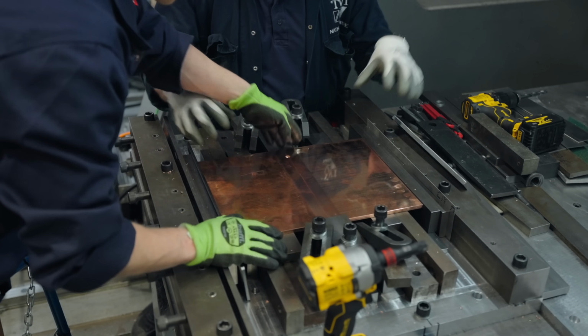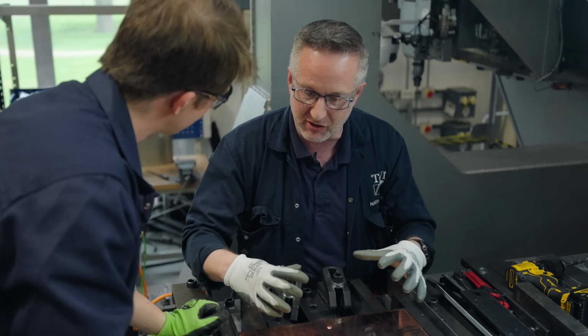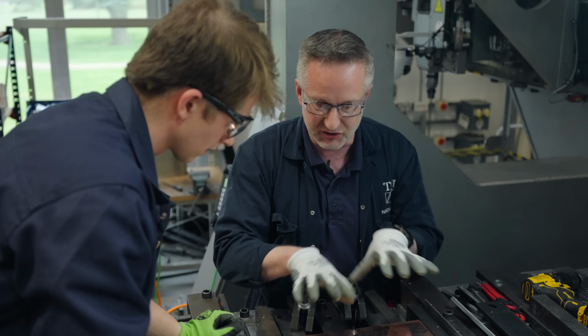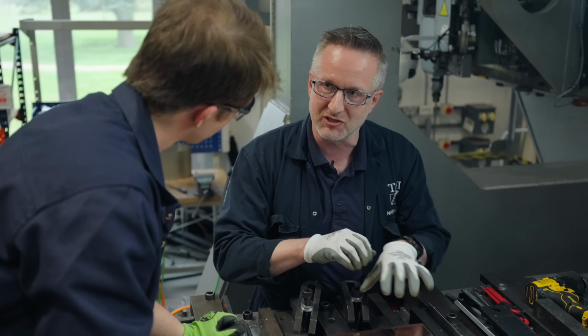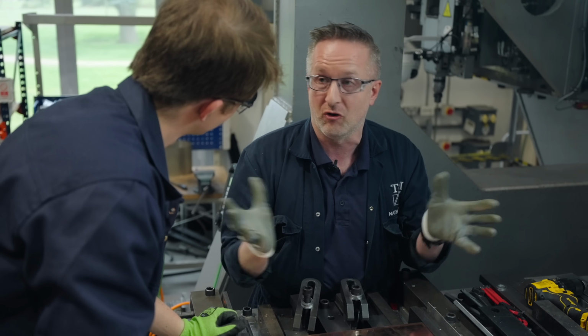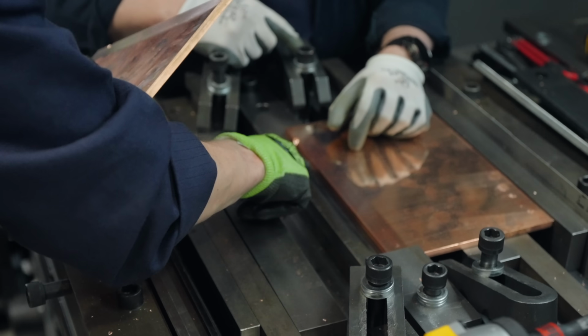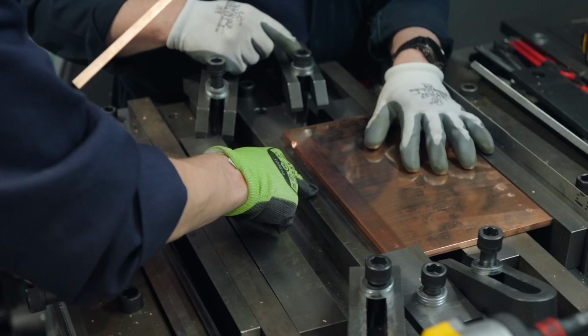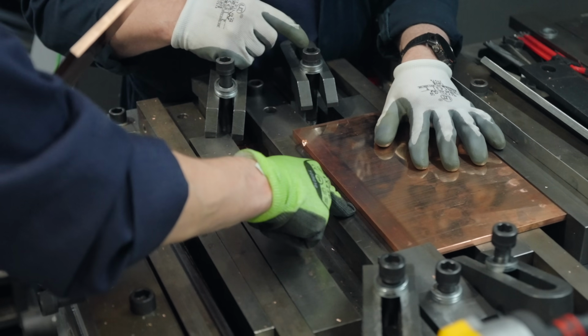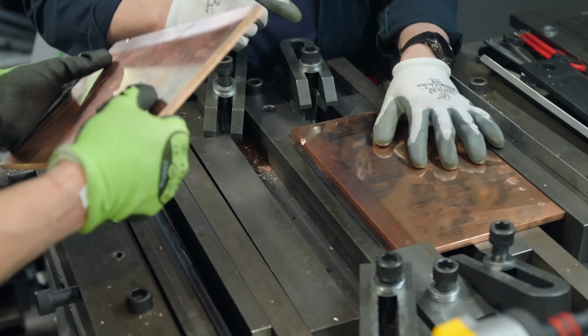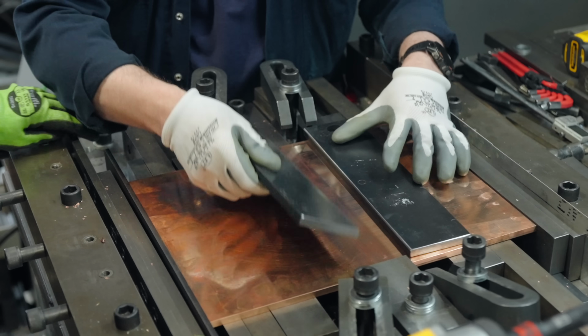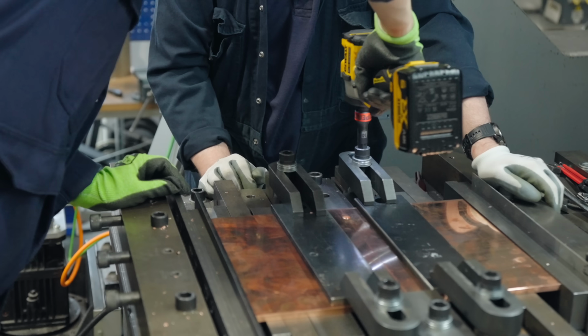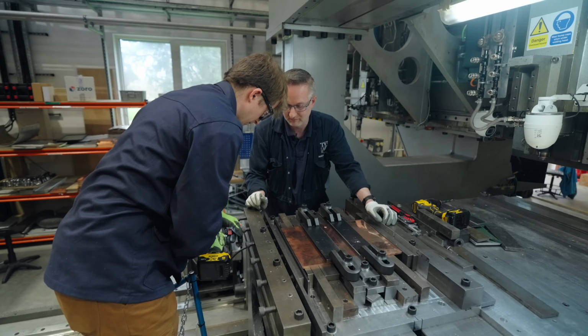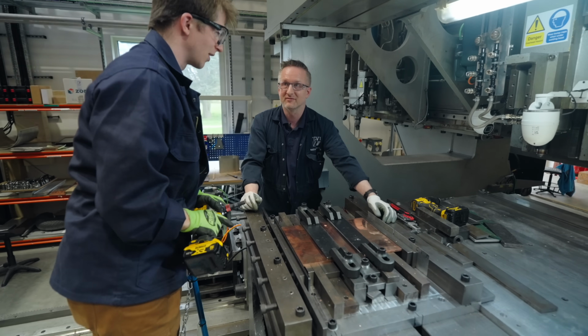With friction welding, we always have to clamp material very tightly to stop it moving around. Because if we start having parts that move around, we're not creating any friction or heat. You don't have any gap on the bottom, it's going straight on the steel. So you're going to get a full penetration weld, even though it's straight backed onto steel. Straight back onto the steel. What? I don't think it's going anywhere.